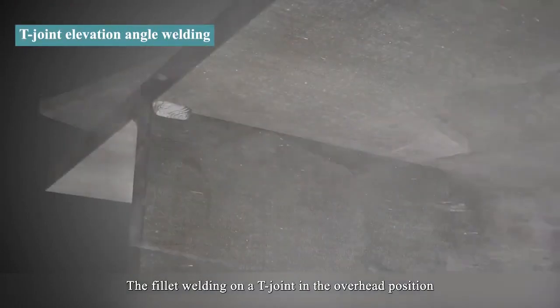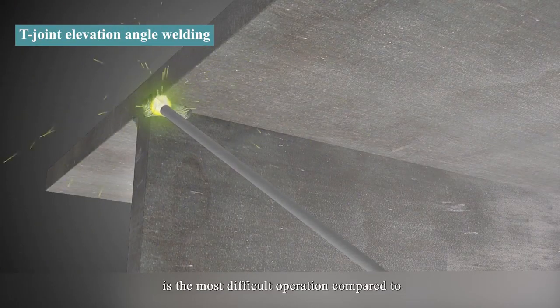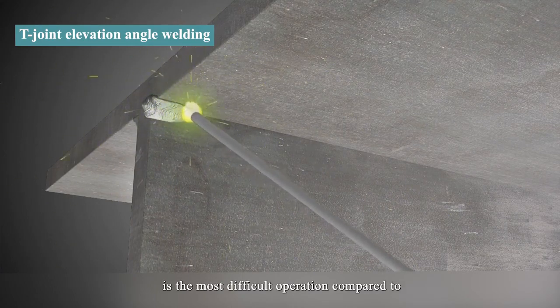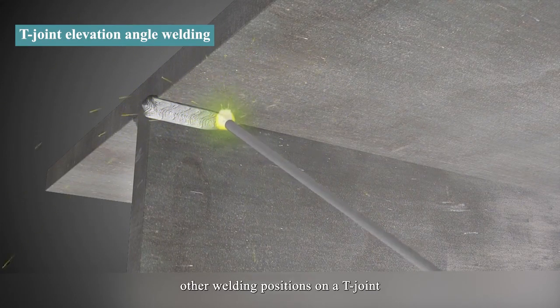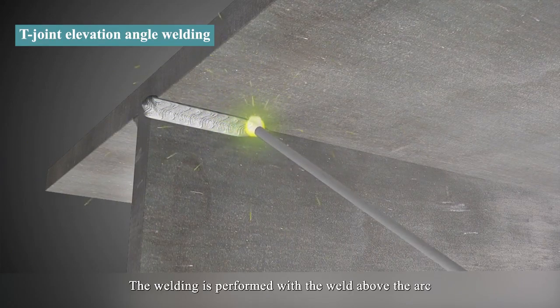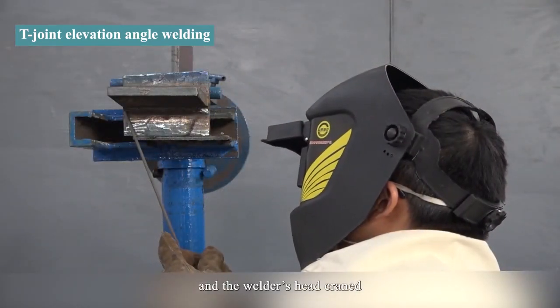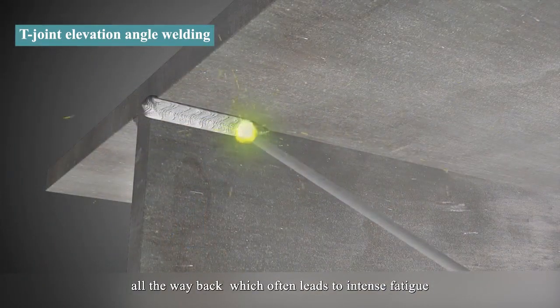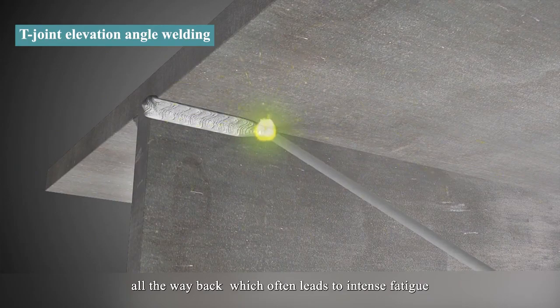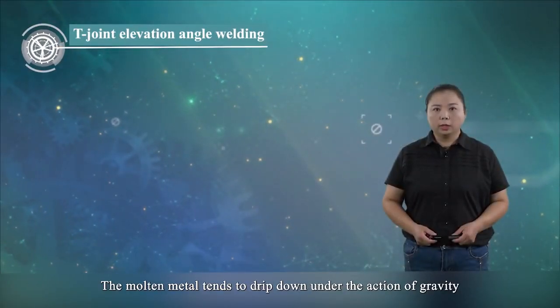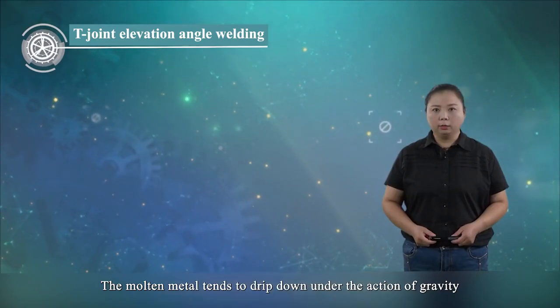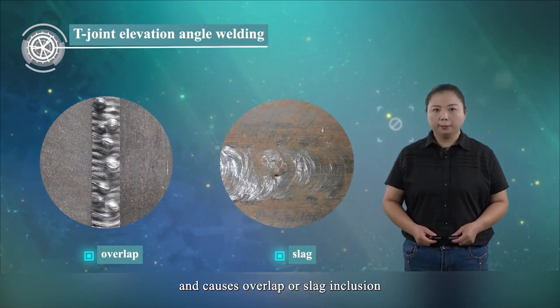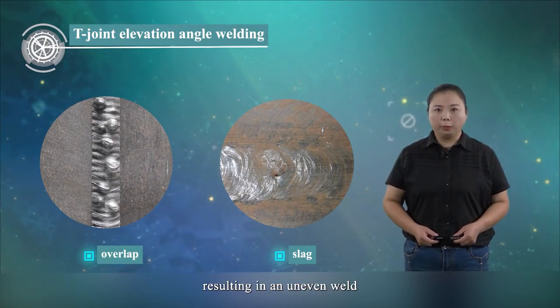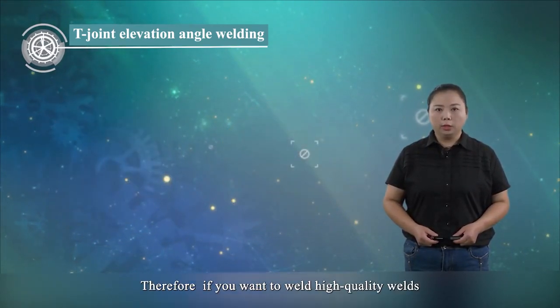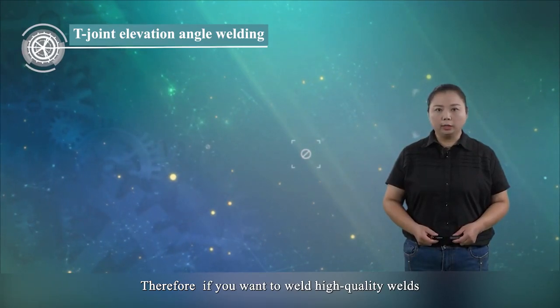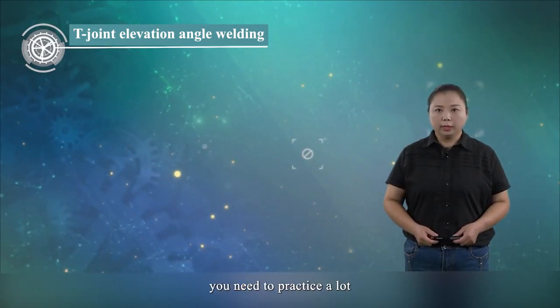The fillet welding on a T-joint in the overhead position is the most difficult operation compared to the other welding positions on a T-joint. The welding is performed with the welder below the arc and the welder's head craned all the way back, which often leads to intense fatigue. The molten metal tends to drip down under the action of gravity and causes overlap or slag inclusion, resulting in an uneven weld.